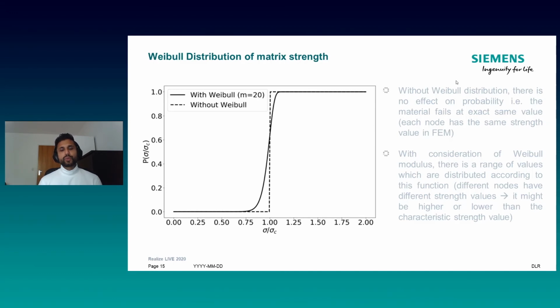In the earlier cases, what we did was we took a particular value, for example, 100 megapascal as our matrix strength, and this property was used at all the nodes. Right, but in our material, we know in ceramic, we don't have the same strength at each and every point. There are some defects, and that's why we have certain points where the strength is higher, and certain locations where the strength is lower.